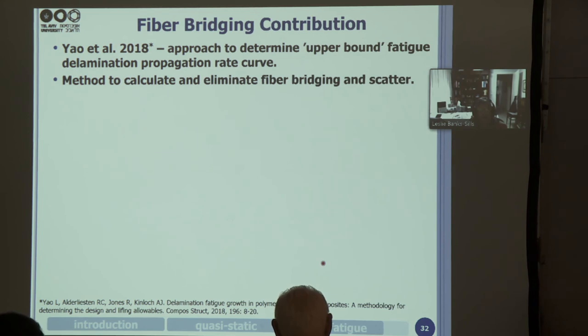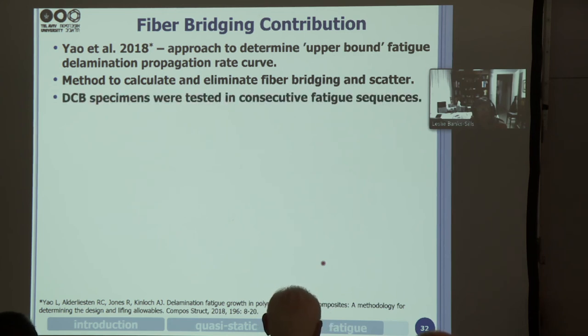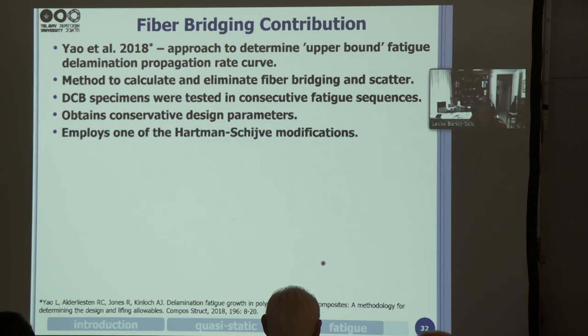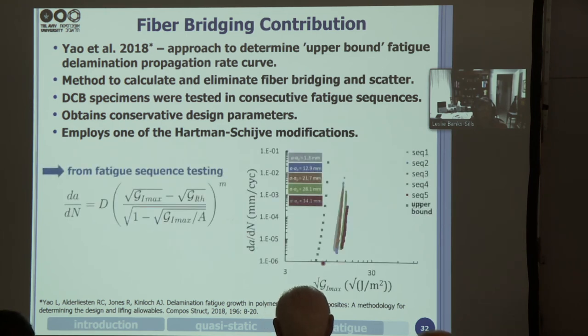There was a paper by Yao et al. in 2018, where they get an upper bound fatigue delamination propagation rate curve. And this is the one in which we have to do sequencing. We carried out 5 sequences. So they gave us a method to calculate and eliminate fiber bridging and scatter. So DCB specimens were tested in consecutive fatigue sequences, and this allows us to obtain conservative design parameters. Again, it uses one of the Hartman-Schijve modifications, the same one that we used before. And here are the 5 sequences.